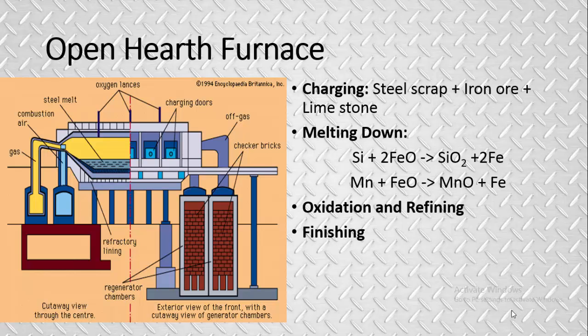Combustion instantly takes place. Currents of flaming fuel sweep over the hot metal, creating temperatures above 3000 degrees Fahrenheit. Excess carbon and impurities are burnt out. The silicon reacts with ferrous oxide, iron oxides, to form silicon dioxide and iron, and the manganese reacts with iron oxide to form manganese oxide and iron. Oxidation and refining also take place in this process.